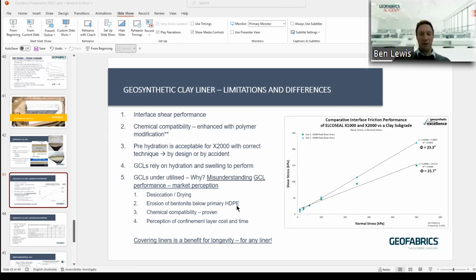Erosion of the bentonite below primary HDPE, we've got a whole range of testing. I think I've got a chart in a minute, but a whole range of testing to show that our GCLs do not erode, and that comes down to the way that it's made up with the polymer modification. It's actually literally bonded very well to the bentonite we've got. So it does come down to chemistry. It's not just a matter of adding a heap of polymer, because the polymers can wash out if you add too much. But I wouldn't be too concerned about erosion with our GCL. And we've got tech notes to back that up.